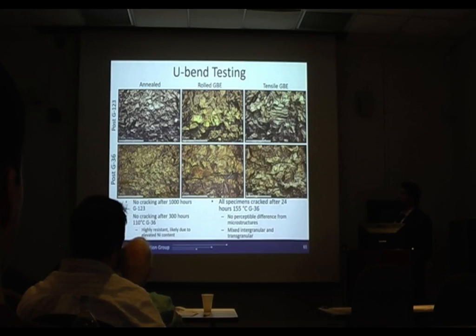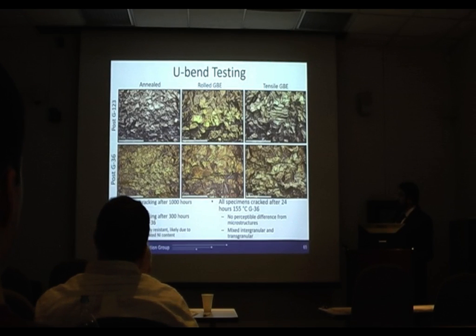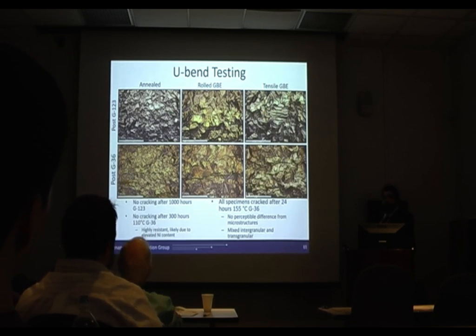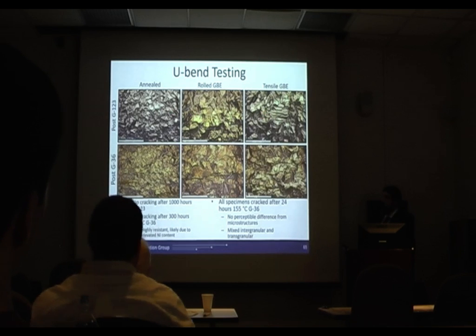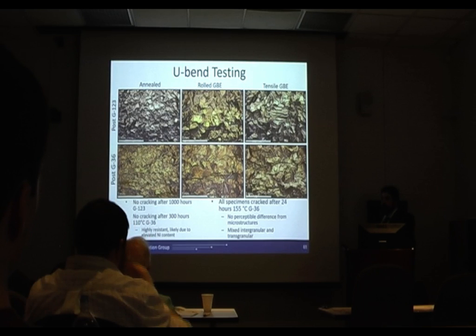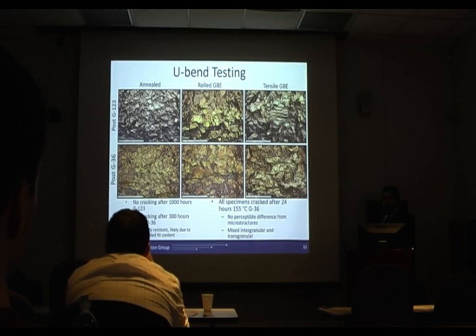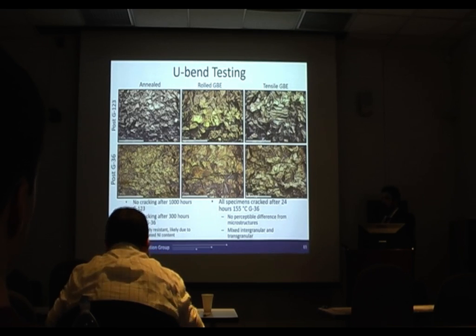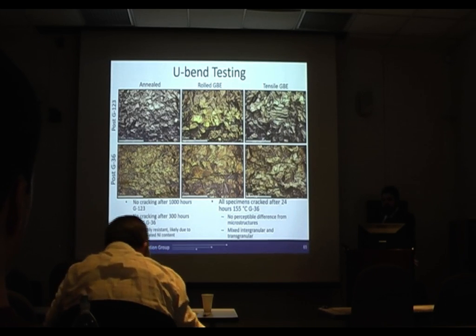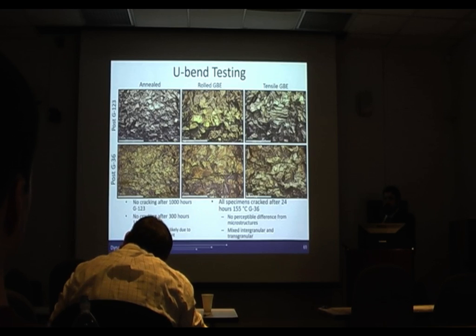What I found though after that testing in the top row is not a single one of our specimens showed any cracks at all. So we went back and we did the G36 test, and that's magnesium chloride. It's known to be much more aggressive, but we did it at 110 Celsius, which has been shown to promote the corrosion cracking. And after 2 weeks, we still had no cracking.